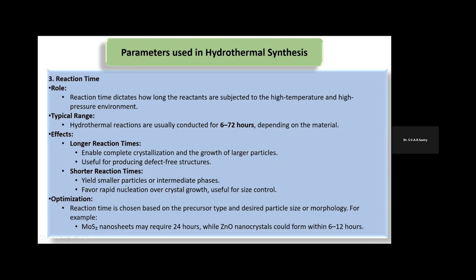Whereas shorter reaction times give smaller particles or intermediate phases like clusters. It also favors rapid nucleation over crystal growth and is useful for size control as well. So again, we have to optimize, and it is observed that molybdenum disulfide nanosheets, two-dimensional nanoparticles, require around 24 hours, whereas zinc oxide nanocrystals can form within 6 to 12 hours. So depending on different types of materials, we have different optimal times.